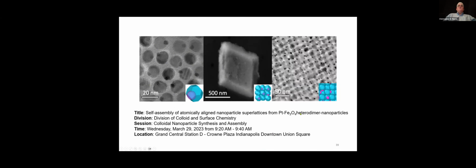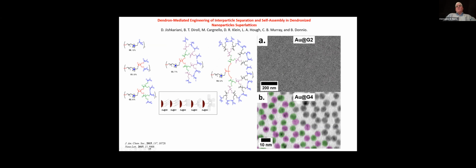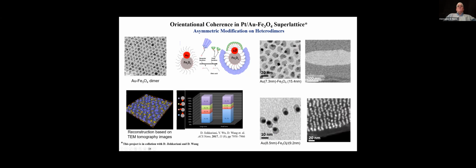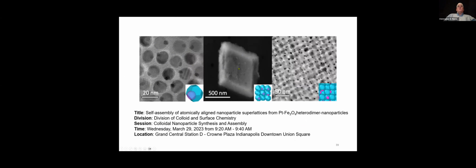So as we begin to use those types of assembly strategies, then we can start to differentiate the binding of those ligands on different parts of our systems. We can grow different types of heterostructures, so we make the inorganic more complicated while getting an expression of the different components of the organic. Now we have systems that are inherently surface active. They orient with polar groups on one end and non-polar groups on the other. So these will begin to organize both as membranes with a high degree of orientational order, or even into three-dimensional crystals, as shown in this example, where now you have a system which has magnetic and metallic, magnetic oxide and metallic functions encoded into the inorganic and then oriented by the organization of the systems.